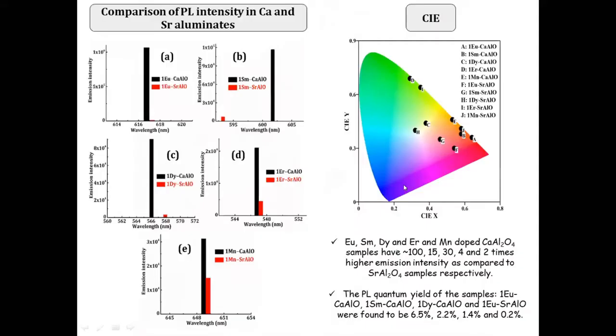And as a comparison of calcium aluminate and strontium aluminate, we find that the calcium aluminates are very good materials as compared to the strontium aluminates for photoluminescence applications. Their luminescence intensity is almost 100 times greater than the strontium aluminates. You can see these graphs. Black lines represent the luminescence intensity for calcium aluminate containing 1 mole% of europium oxide. And red is here, very small, almost 100 times more intense.